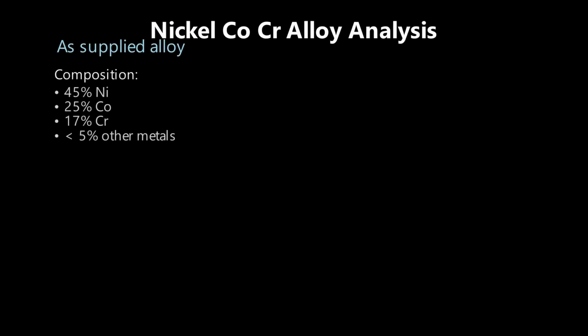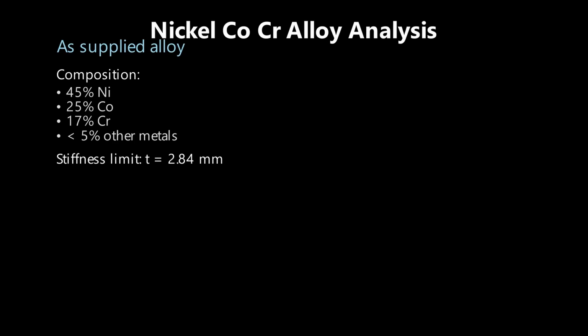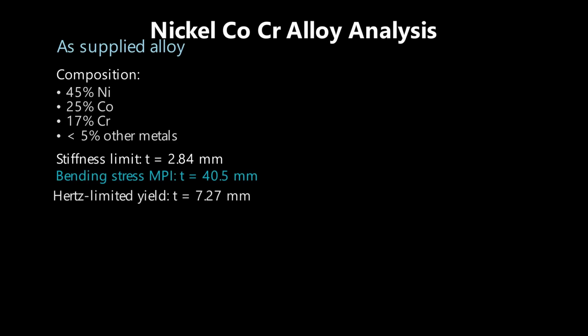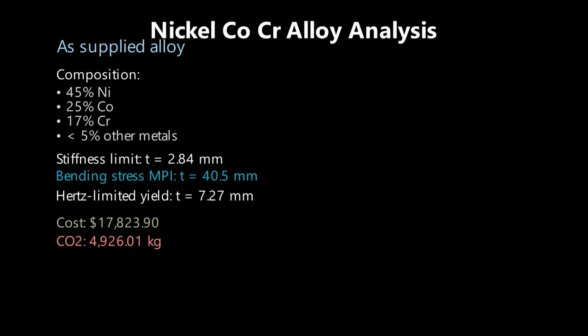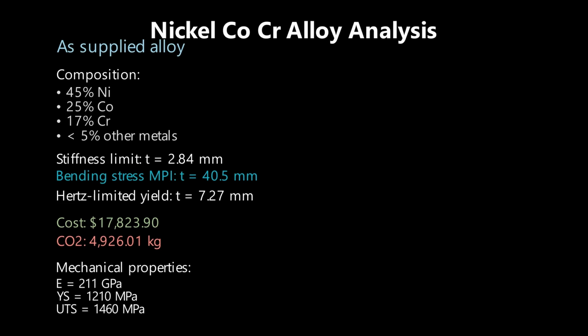The nickel-cobalt-chromium alloy contains 45% nickel, 25% cobalt, 17% chromium, and less than 5% of a number of other metals. According to the yield strength MPI, T needs to be 7.27 mm. According to the bending stress MPI, T needs to be 40.5 mm, or around 4 cm. And according to the stiffness MPI, T needs to be 2.8 mm.